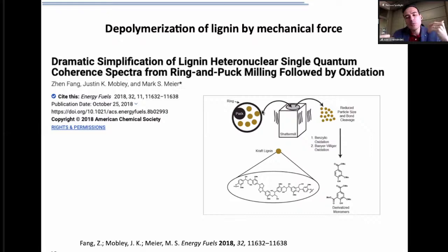And they observed that indeed, when you do the reaction in this type of setup, then the reaction proceeds faster, cleaner, and more selectively. So it seems that there is a technique that could potentially enable the activation of, why not, mechanophores within polymers in gram scales.